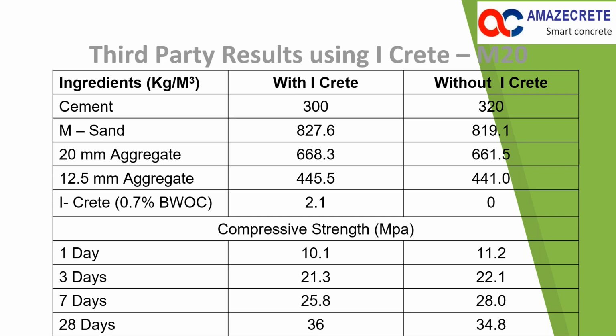So some of the earlier trials, these are third-party trials, which are simple examples to indicate the efficacy of iCrete. The control mix here is an OPC system of 320 kgs per cubic meter, and with iCrete we used about 0.7% by weight of cement content, that is 2.1 kgs, and then here you can see the 28 day strength is similar to the control. So by using about 0.7% or 0.8%, you can get about 20 to 25 kgs per cubic meter reduction. This is one of the very initial trials done in a third-party laboratory.